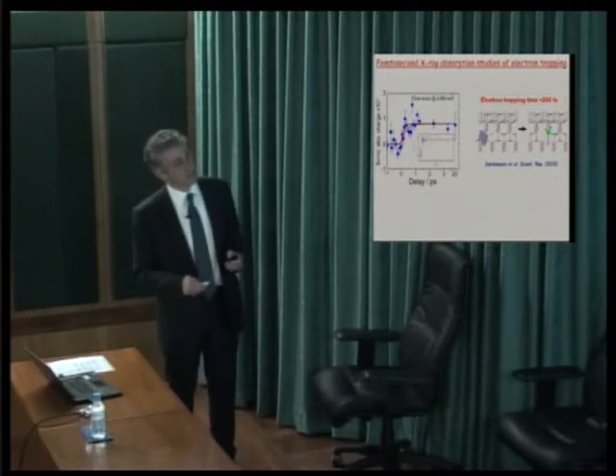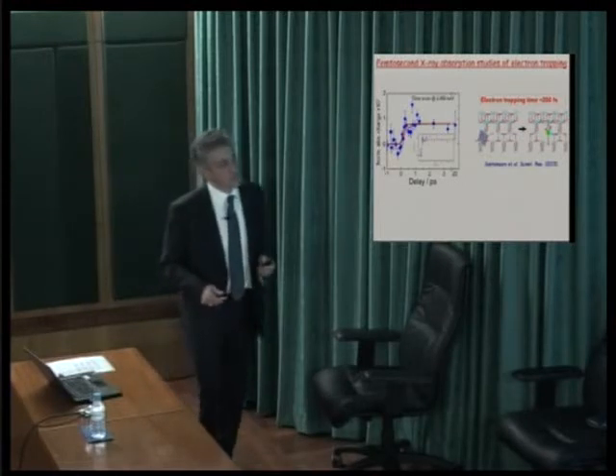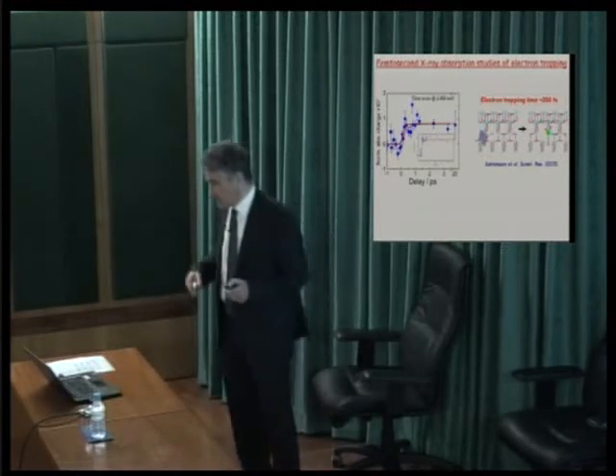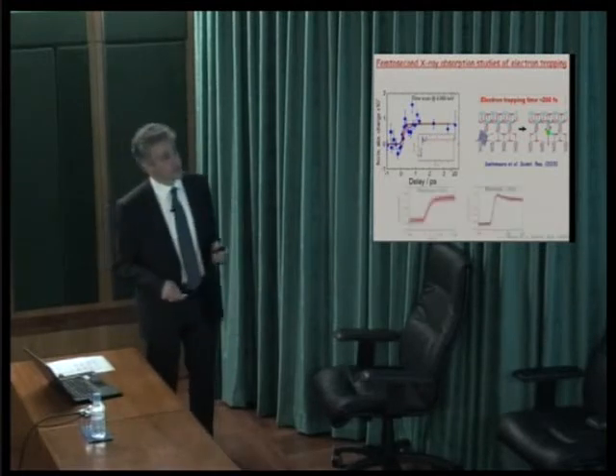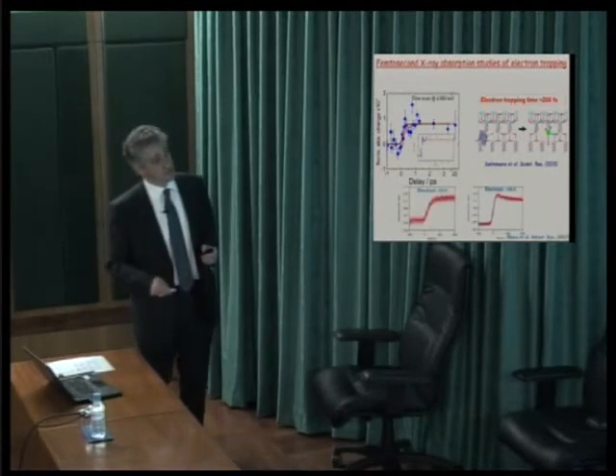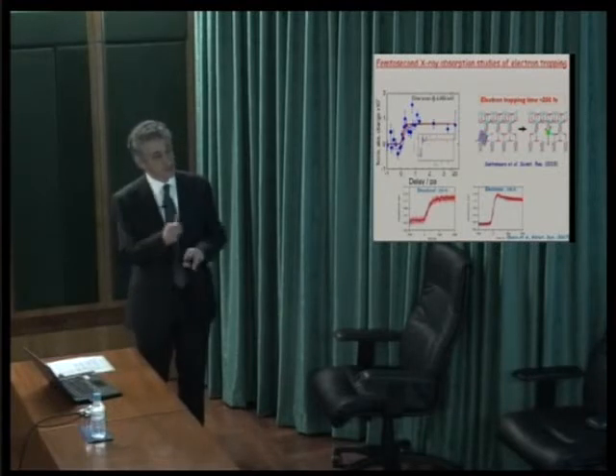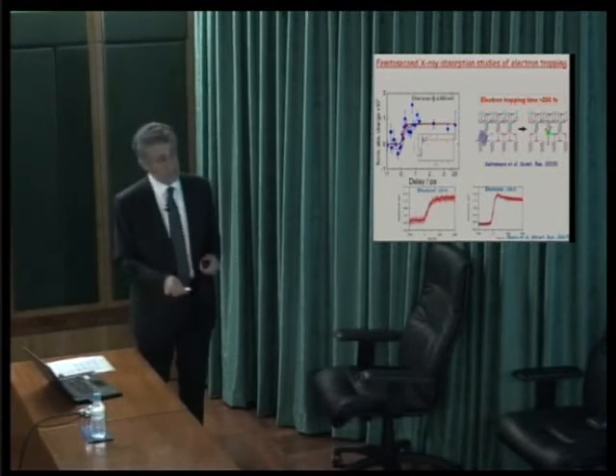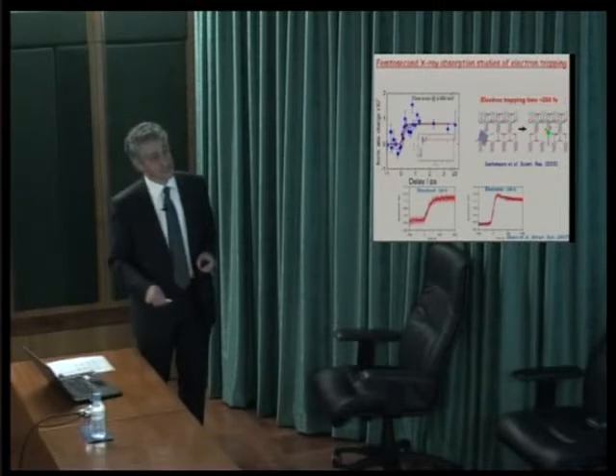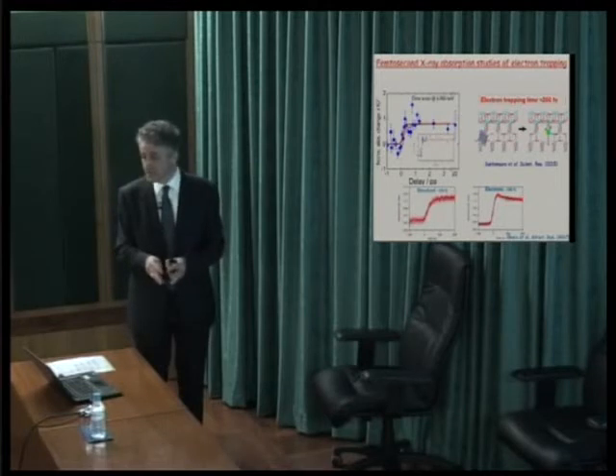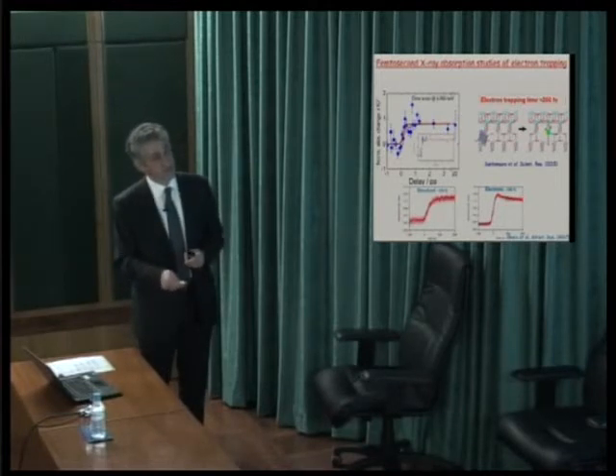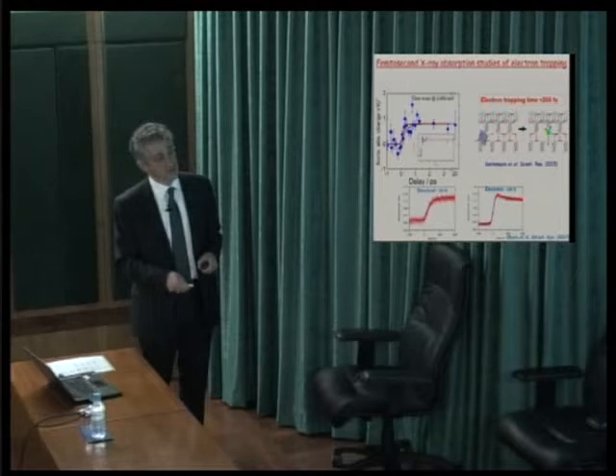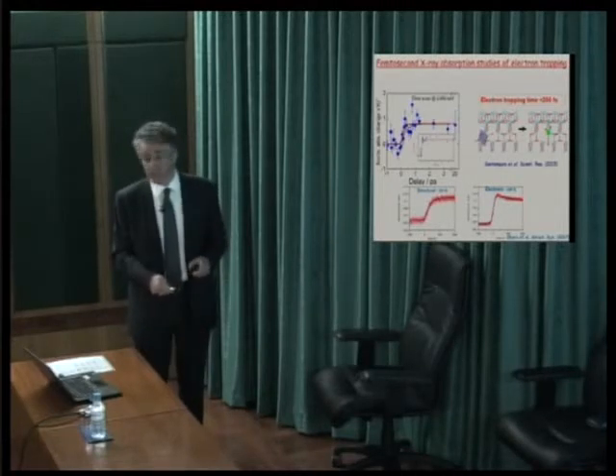And then immediately afterwards, a group in Japan picked up our results and did an experiment with a free electron laser, and you will be struck by the difference in quality in signal to noise. And they could tune in the spectrum to features that are purely electronic or purely structural, and there they saw a different rise time, which makes sense. Electronic structure changes are immediate, probably less than 100 femtoseconds. But then the structural dynamics of these oxygens to move away from the titanium takes time, and you see that the time scale for the structural response is three times that